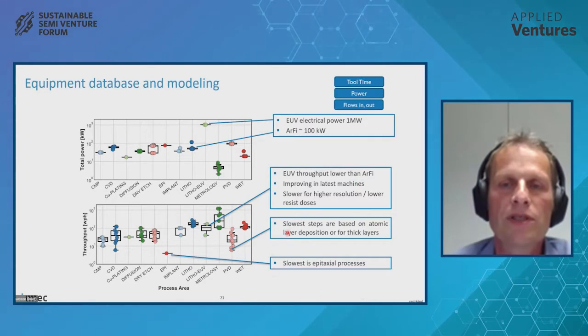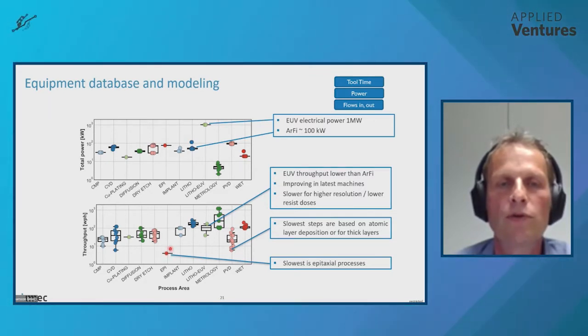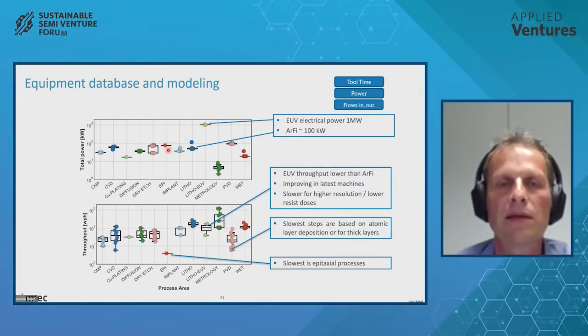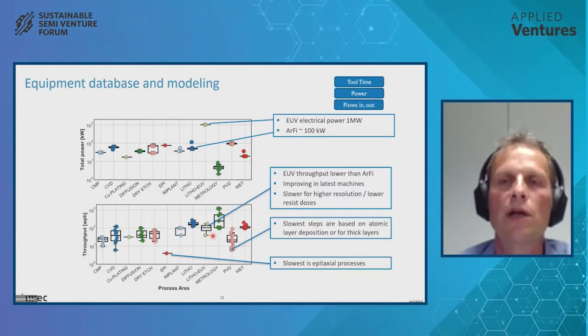The slowest steps are based on atomic layer deposition for very thick layers. So this is actually covered in the PVD part. And also EPI is a very slow process. Now, there are not so many of those, so that has a little bit less impact than lithography, which is used a lot in the process.